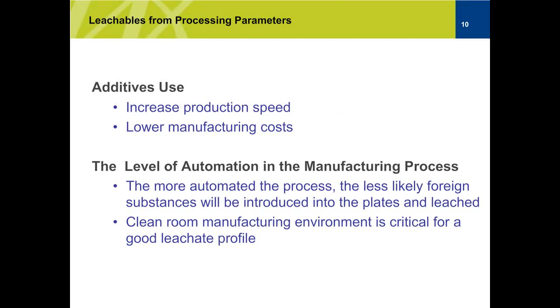So again, during the processing of the injection molding, many companies use a lot of additives, and this is to increase the production speeds, which ultimately lowers the manufacturing cost, and that's where you get a lot of leachables. And then secondly, some companies do not have a fully automated process, and every time you have a semi-automated process, you increase the risk of introducing foreign substances, and those can be introduced into the plate, and they can leach whenever you're doing your assays. Also, manufacturing these plates or labware in a clean room environment is very critical for having good leachable profiles.